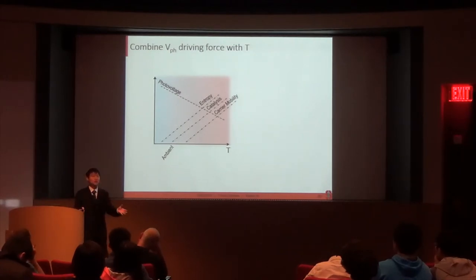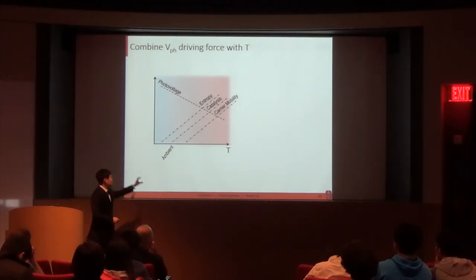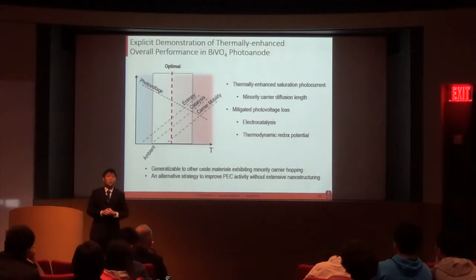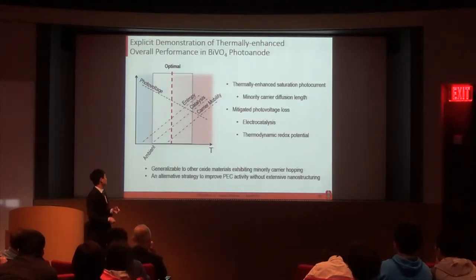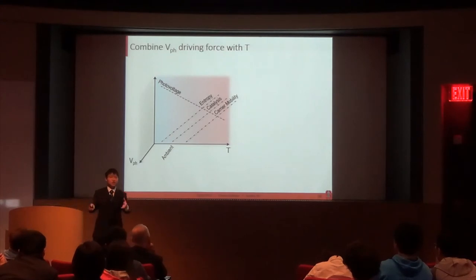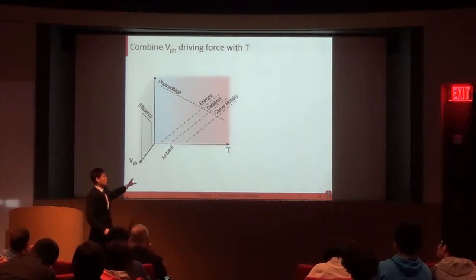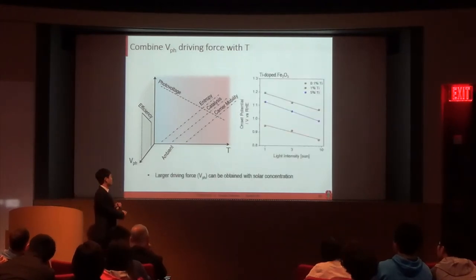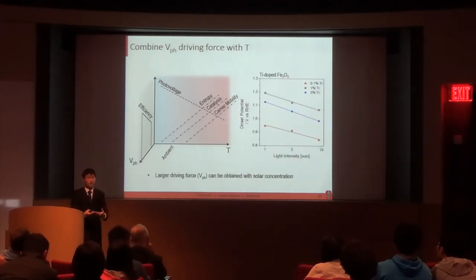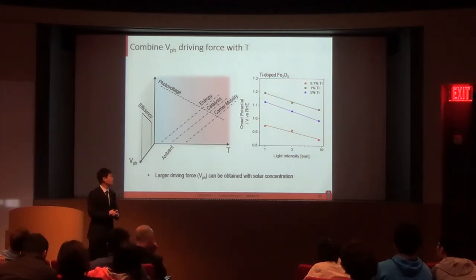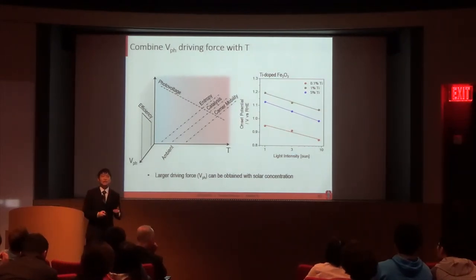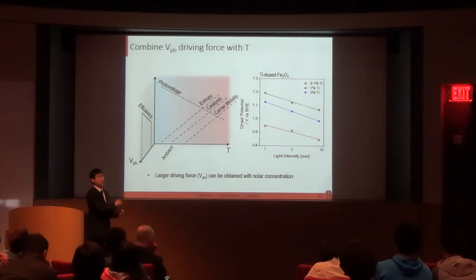So looking back to the fundamental picture, besides tuning the temperature by itself, what we actually want to do is to combine the temperature with the photovoltage driving force. In general, increasing the photovoltage or increasing the driving force usually gives you a higher efficiency. Such a driving force can be achieved by solar concentration, which is well known in solar cells. We also observe that in our hematite photoanode: increasing the light intensity decreases the onset potential.